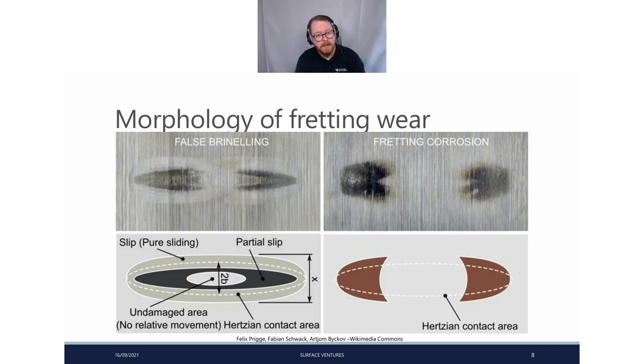And then beneath that, we can see the actual diagram of what's going on here. We have the central, seemingly undamaged area where the actual contact was maintained. This is the section of the wear scar that is undamaged during fretting. The outer area is defined by pure slip, or pure sliding, apologies. And then the more central area, partial slip. So we have essentially a stick section right in the middle. This will move, so then you get slip on either side of that, and then sliding around the outside.